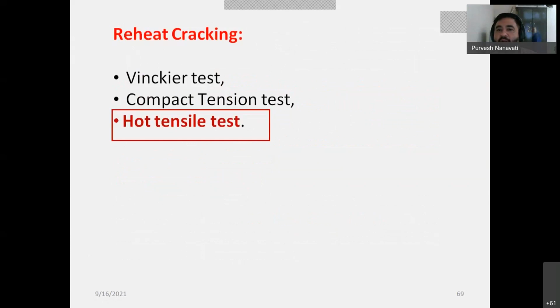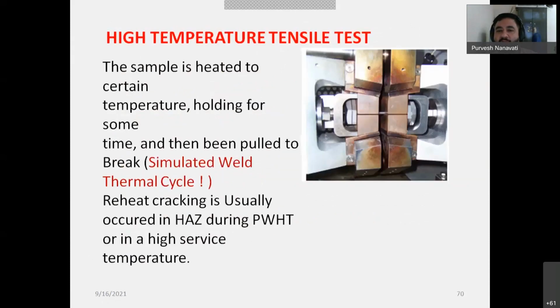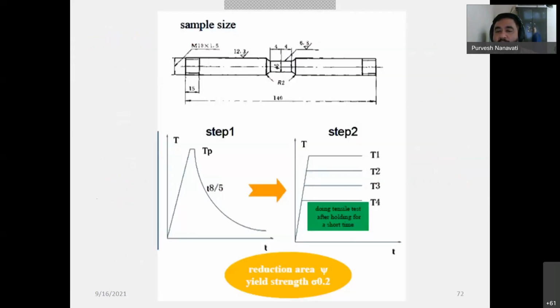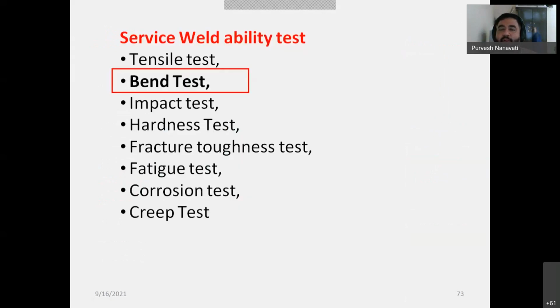Now last is the hot tensile test. This hot tensile test is conducted in the simulated weld thermal cycle test. So what do you do? You apply heating and cooling. Likewise, you see a temperature versus time, you see heating and cooling between the 800 and 500 range. Okay, fine. So the last test is a bend test, right?